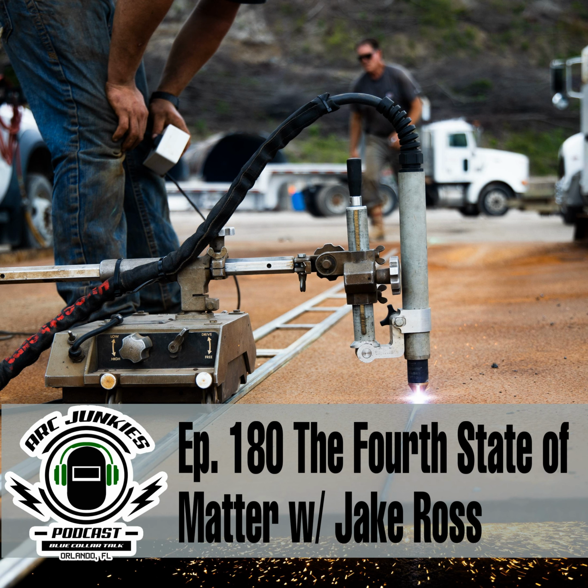What was that first one you mentioned? You mentioned something like a 325 Air or something? So the 30 Air, so PowerMax 30 Air. That is a plasma cutting machine with a built-in air compressor that goes up to 30 amps. So again, we always ask, what kind of power are we looking at? Well, that's 110 to 240, and you get a different range of power based on which voltage you're using.